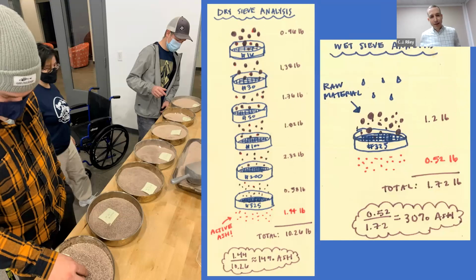If we get back to the material side of things, here's some of the raw ash material laid out in sieves, and you can see that some of the material is fairly coarse, like a coarse sand, and some of the material, really the ash that we had determined was more active and performed as a pozzolan, was the finest ash that we had. And it would pass, as you can see here, a number 325 sieve. If you're not aware of sieve analysis, a 325 sieve produces something that's about as fine as a makeup compound. You can barely feel it.